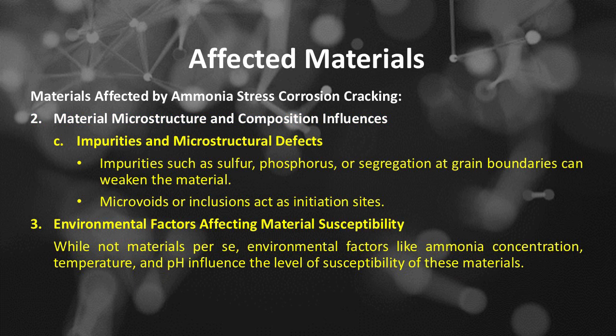Number C, impurities and microstructural defects. Impurities such as sulfur, phosphorus, or segregation at grain boundaries can weaken the material. Microvoids or inclusions act as initiation sites. Environmental factors affecting material susceptibility. Environmental factors like ammonia concentration, temperature, and pH influence the level of susceptibility of these materials.